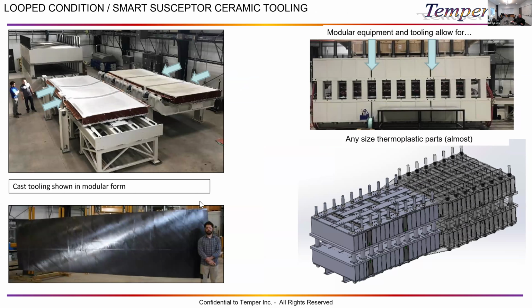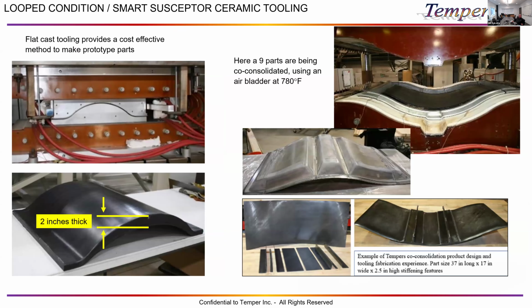So from the simplest case, this was 15 feet long. We could go out to 35 feet long, easy enough, by just adding more modular sections onto the restraint and make it as long or wide as we needed. This type of pourable ceramic tooling for low volume also works for bonding and co-bonding.